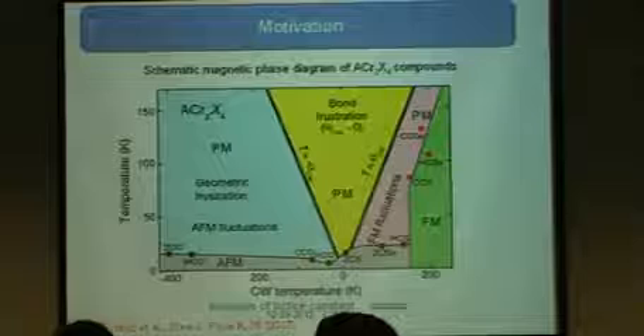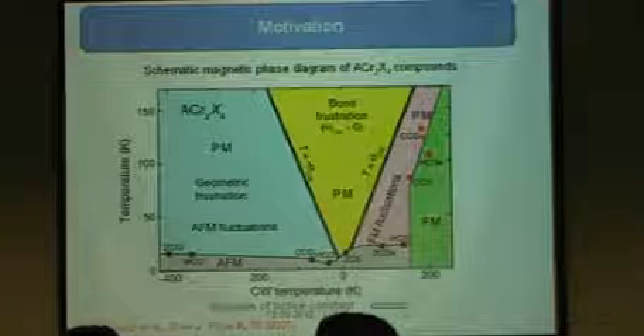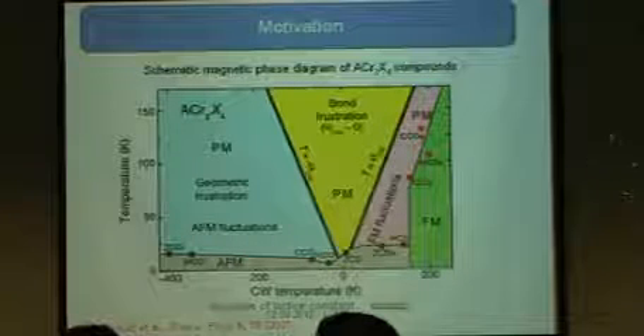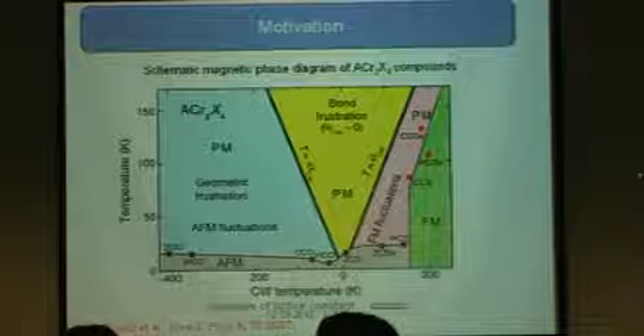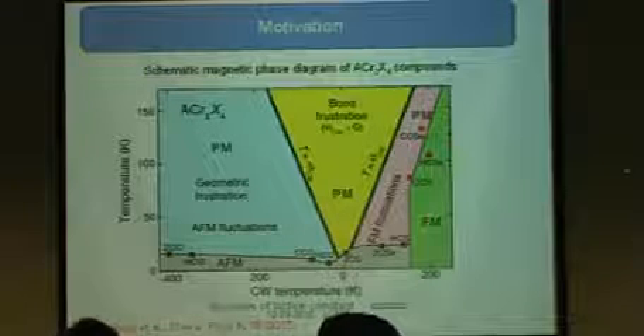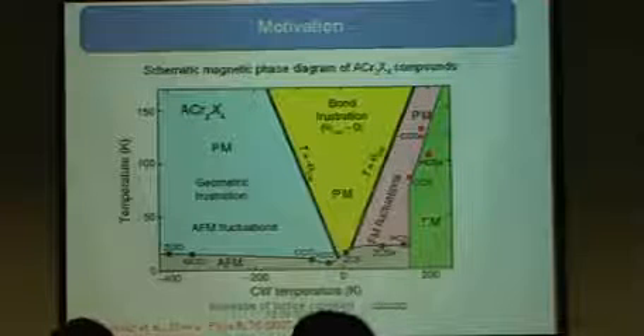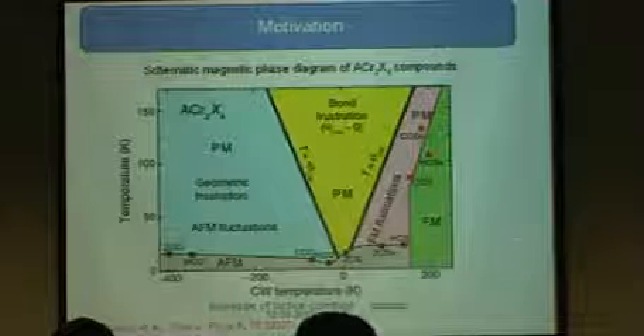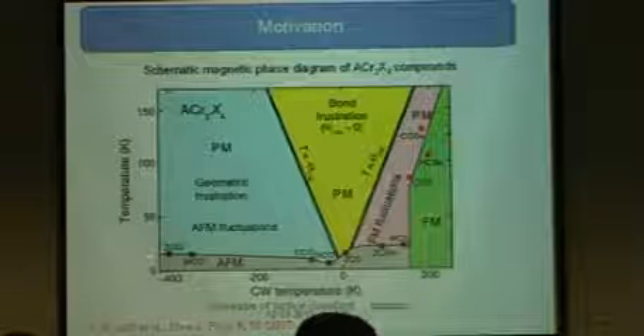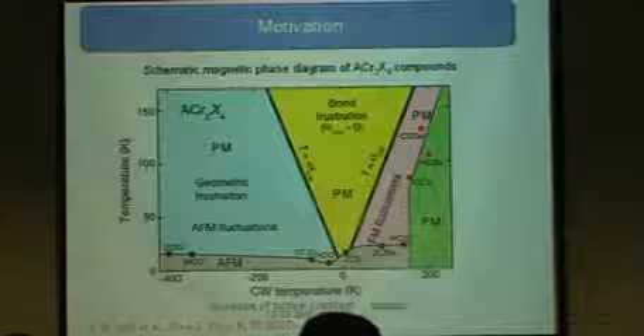Okay, in case of frustration. But when you call this bond frustration, here antiferromagnetic and ferromagnetic interactions are almost of the same order. So it's just terminology where they use this as bond frustration. And when you go here, you get more ferromagnetic, because here you have a small lattice constant, so direct chromium-chromium interaction is possible.